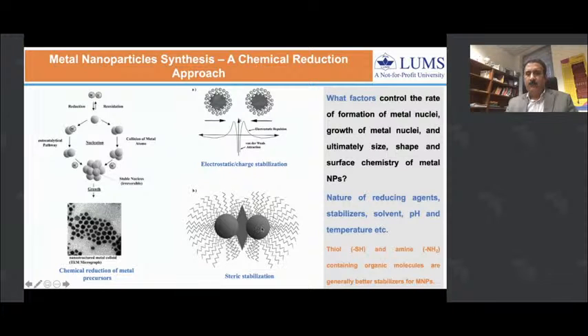But if you want to make these particles extremely stable, you need to covalently attach long chain molecules which have thiol or amine at one end that actually attaches almost covalently to these metal nanoparticles. Due to steric bulk of these coating ligands, the nanoparticles do not agglomerate, and you can dry them and keep them for many years whenever you want them.